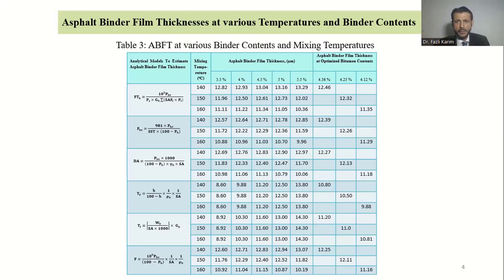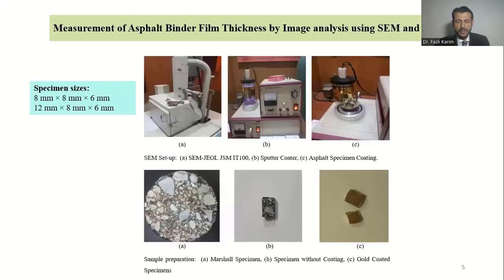And the film thickness ranges from 9.88 to 12.46. Now, these are the film thicknesses assessed analytically for the mix design carried out at 3 different temperatures for the models shown. Now, the next phase was basically to check the validity of these film thicknesses using micro level techniques.